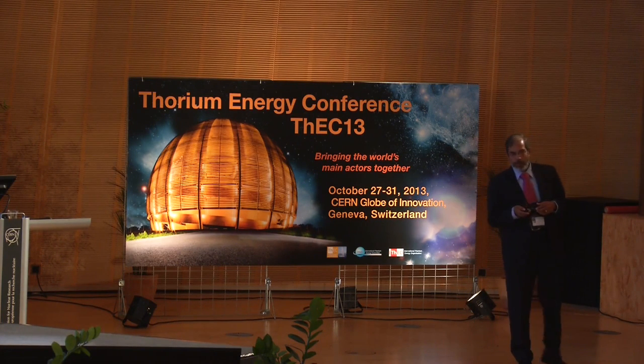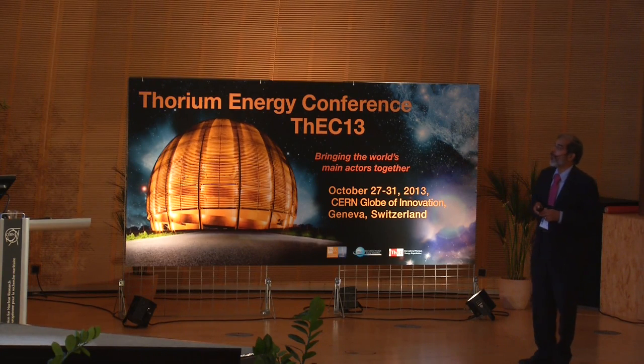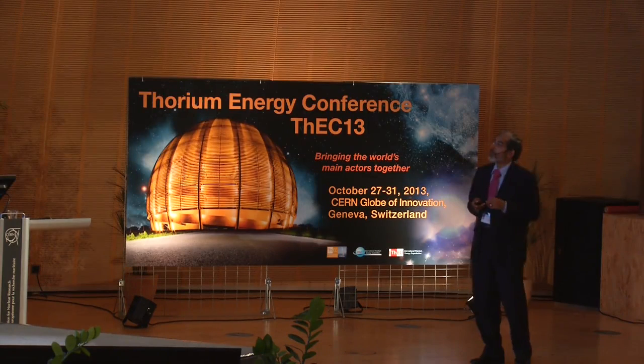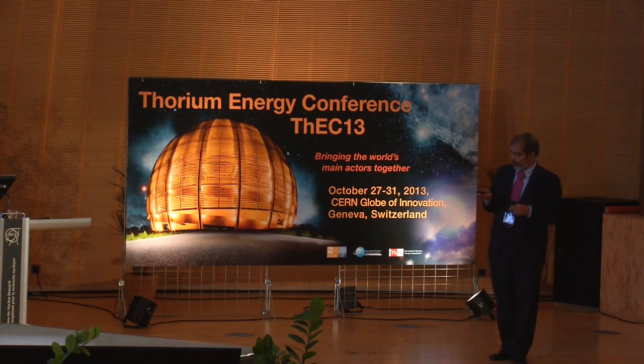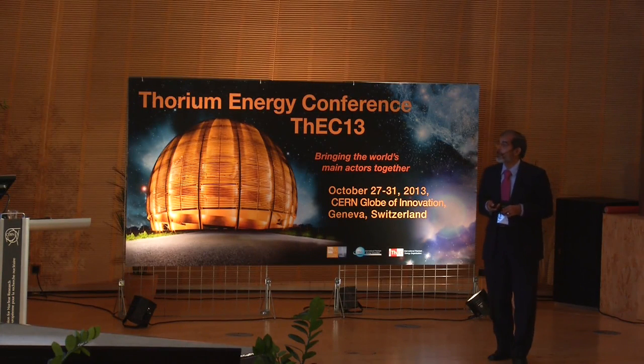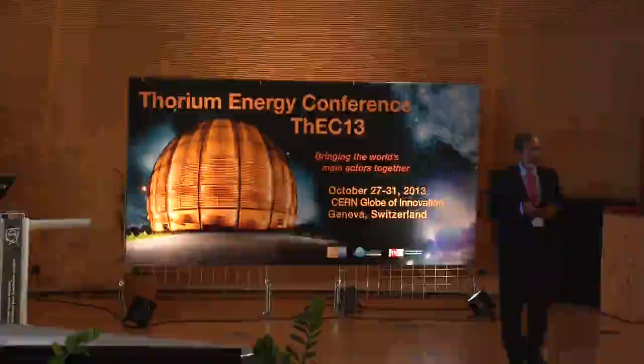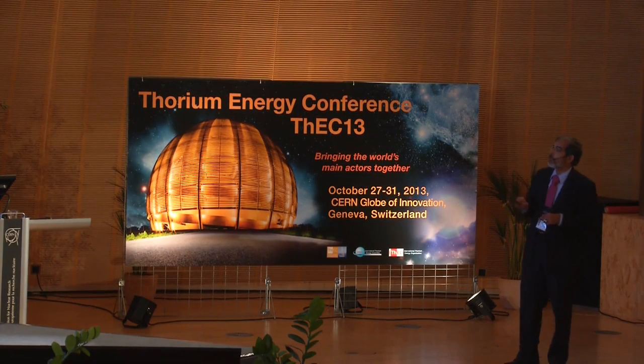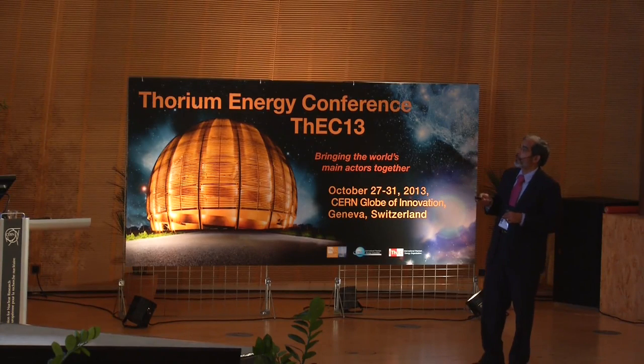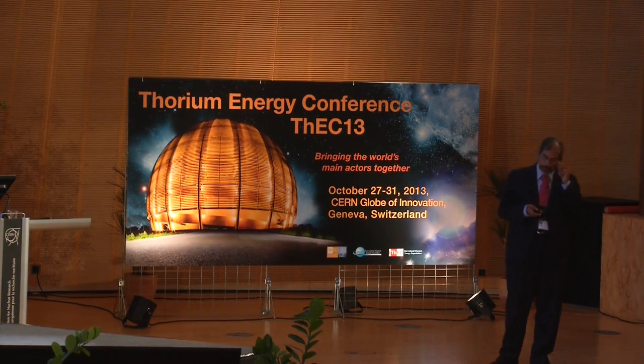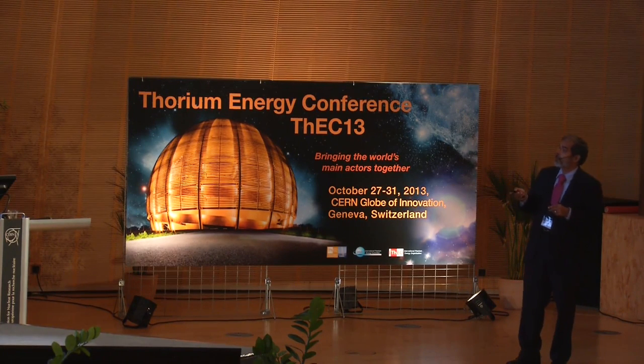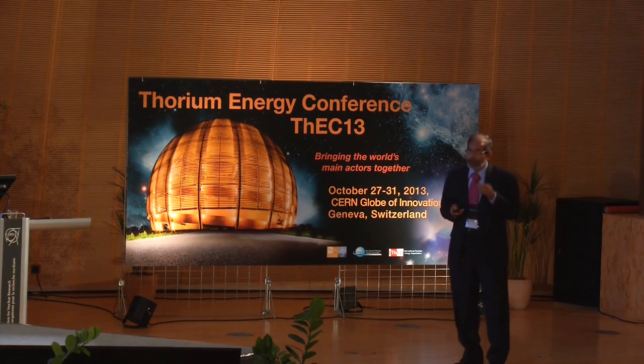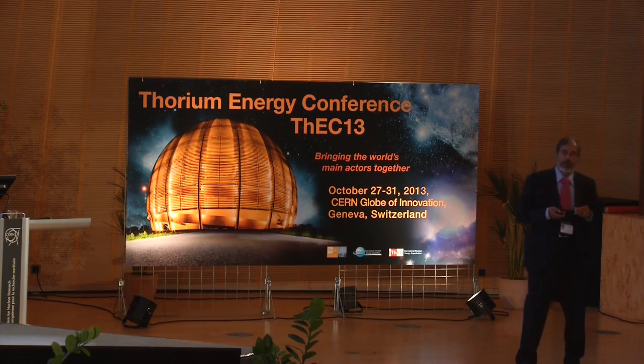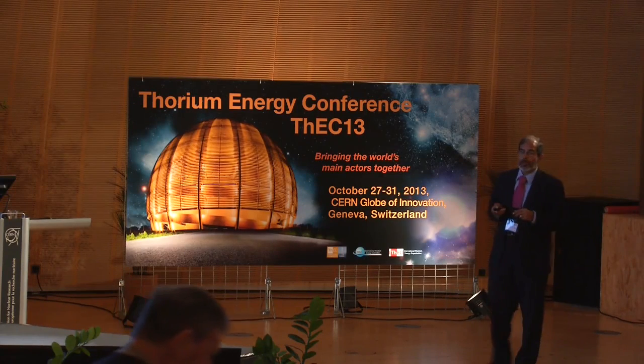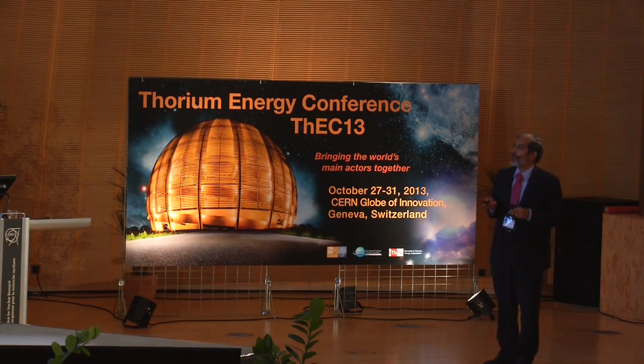And some of the developments which we have already done: we have been able to successfully produce these triso-coated fuel particles, albeit on surrogate material. And the technology for these carbon-carbon composite tubes, which are used as fuel tubes, has also been mastered. Then here are these high-density beryllia blocks, which have also been manufactured. We have been successful in machining these graphite blocks, and for high temperature applications, especially the oxidation resistant coatings, some of these have already been developed on a lab scale, but have to be commercialized.